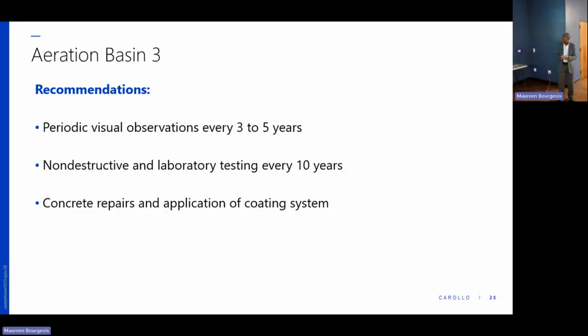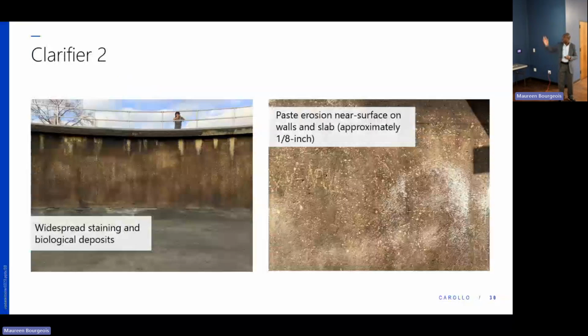Let's go to clarifier number 2. Again, same thing with the staining and biological deposits on the clarifier. We see that in the picture. And then we see the paste also being eroded towards the surface because of all the turbulent waters happening there with the moisture and the air-rich environment, and then bacteria. So all that takes place there. But it's approximately 1/8 of an inch on the near surface.